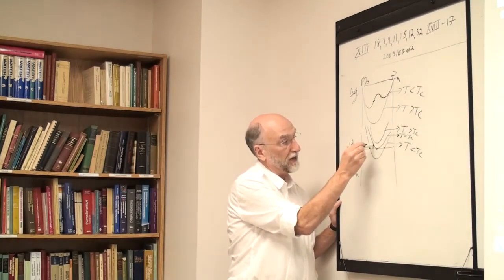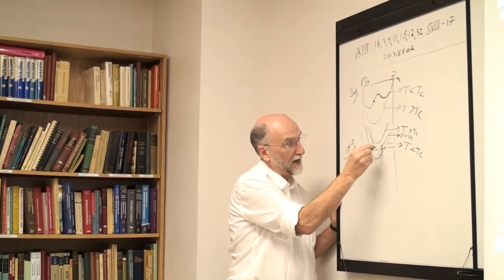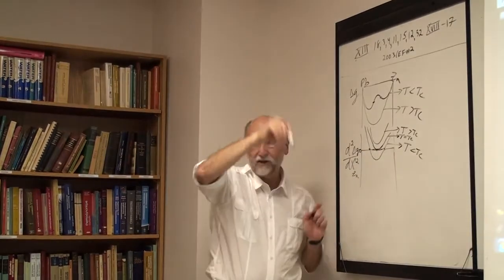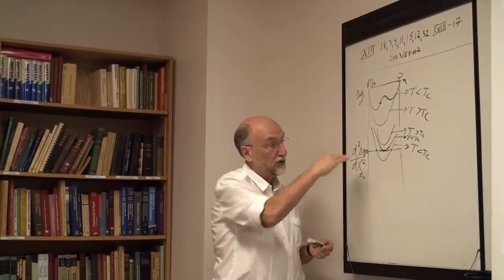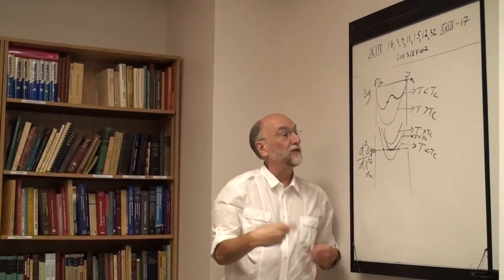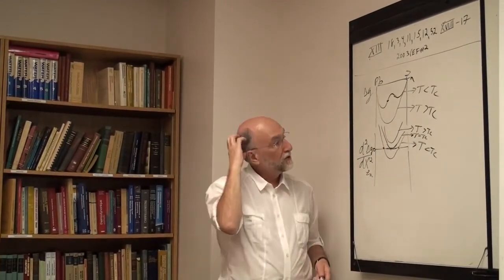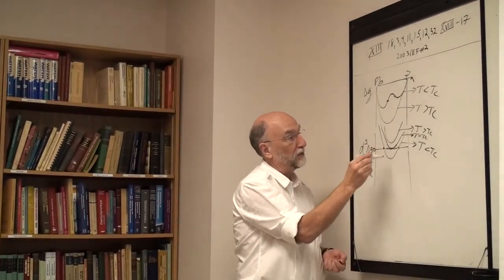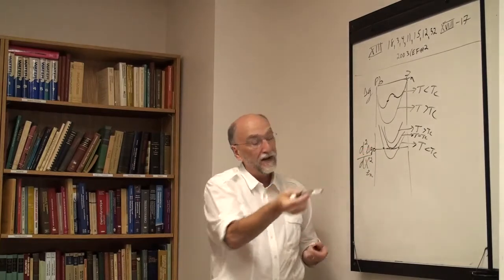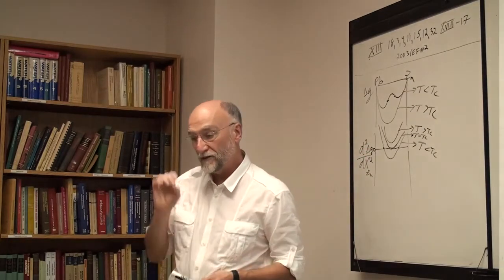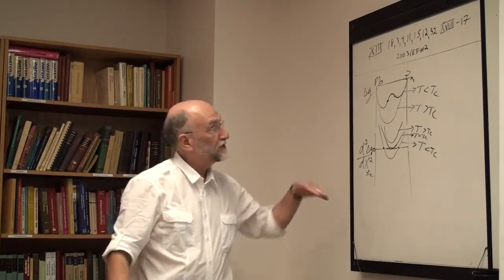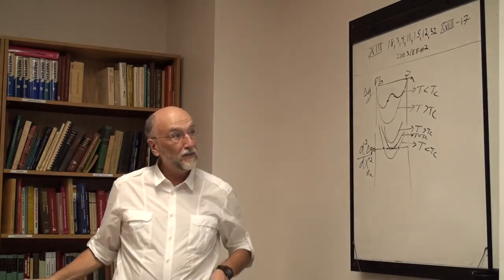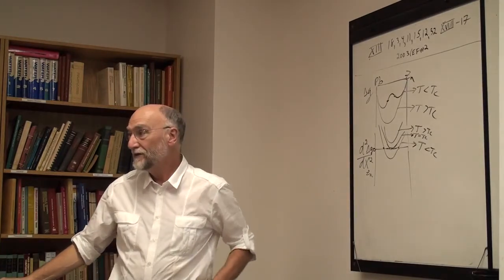Secondly, it's clear that it goes to zero at the minimum value of this second derivative curve, so the slope of the second derivative is also zero. In other words, the third derivative is zero. So the two criteria for the critical point are that the second derivative is zero and the third derivative is zero at the critical point. That then permits you to calculate the two constants A and B, because now you have two equations.